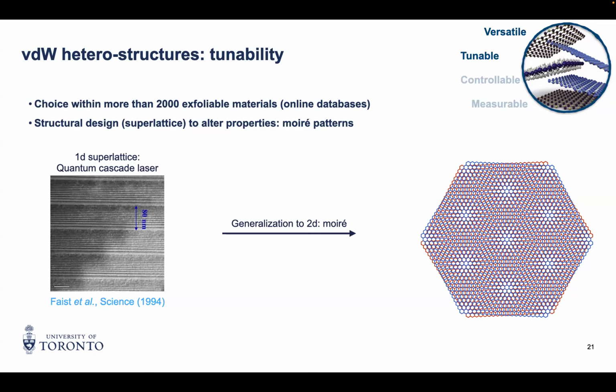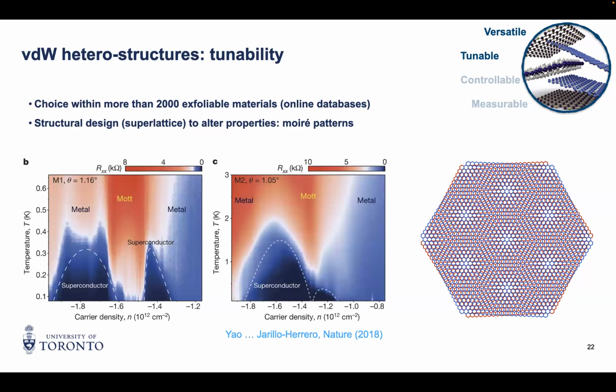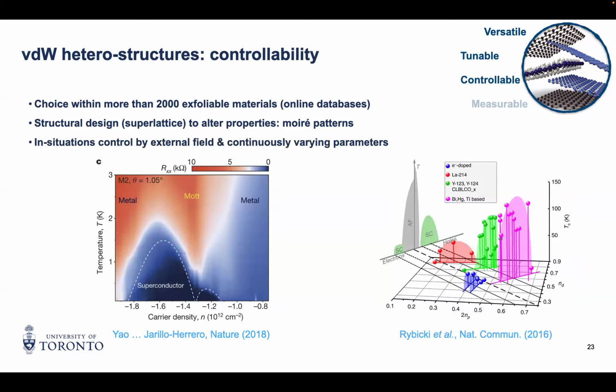And the fact that you have an interference pattern doesn't tell you that they are useful for anything, as they were for quantum wells. But what started the field of Moiré materials was an experiment in 2018 that showed that having those superlattices could really change the physics of the system. By taking two layers of graphene and twisting them by about 1 degree, you could get a superconductor, while none of the monolayers by themselves is superconducting. So it tells you that it's one more knob that you can play with to get tunability or to access new physics from stacked monolayers. Right.